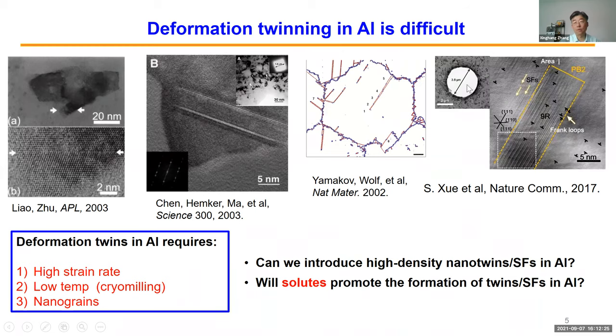And MD simulation shows yes, high strain rate deformation can also introduce twin boundaries in aluminum grains. And this is another example where we did a projectile impact into a TEM foil and generated a hole using a silica sphere, and then surveyed the grain orientation evolution. And we found pretty large, substantial stacking faults, the so-called 9R phase, in pure aluminum. So yes, you can introduce twins in aluminum, but you need one of these three factors: either high strain rate shock, low temperature cryomilling, or nanograins, tiny grains. This is not helpful if you want to introduce abundant twins and use twins to tailor strength; you have to come up with something else.